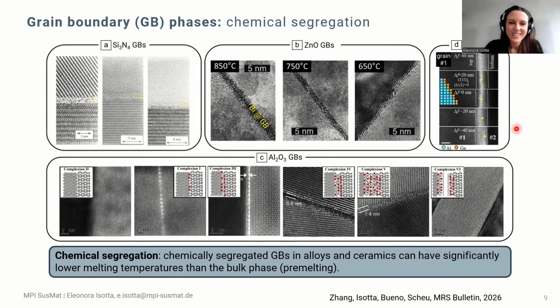Basically, the idea is that in certain compounds, for example alloys or ceramics, the grain boundary could actually take on a different chemical composition. This could also be caused by the fact that the boundary has a significantly different melting temperature than the bulk phase, which is called pre-melting. In such conditions, the grain boundary basically forms what is called an intergranular film with a different composition.